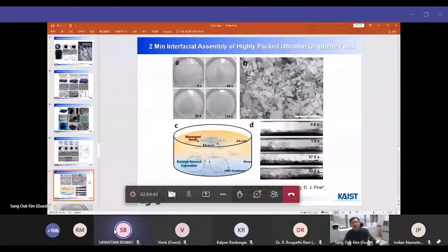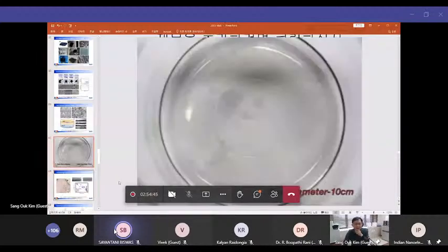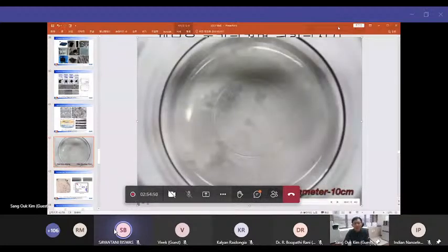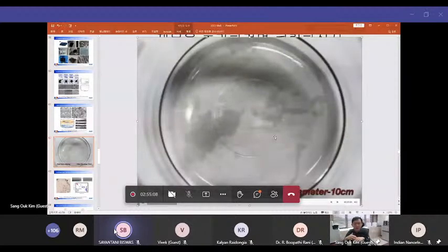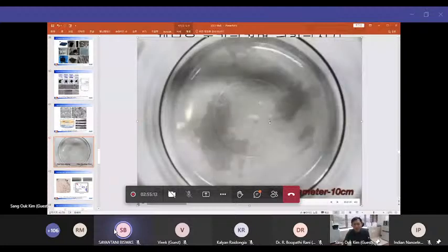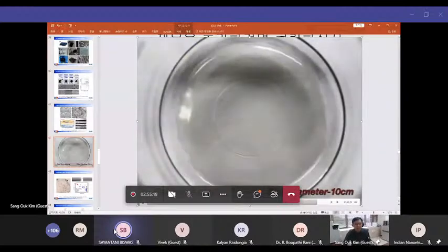And next one is the Marangoni effect. Actually, I told you that surface tension can be useful. This is a real-time movie showing the 2D material assembly at the water surface. Originally, graphene particles are dilutely dispersed over the entire dispersion, but they spontaneously floated at the surface and undergo lateral assembly. And the assembly is very dynamic, like a living system. So we could attain a 10 centimeter diameter assembly in a 2-minute process.